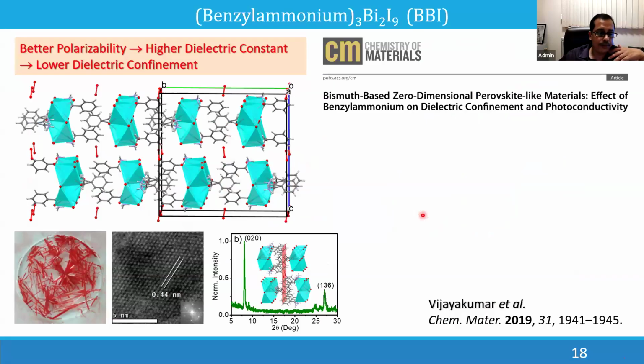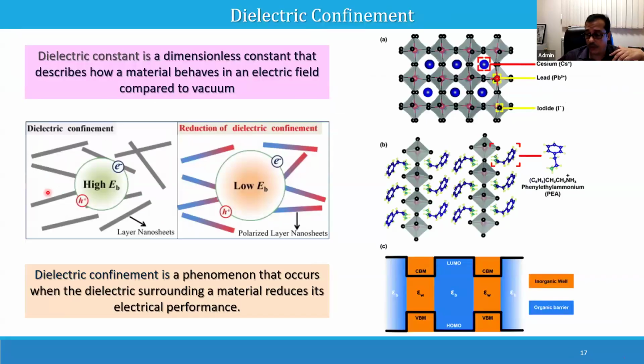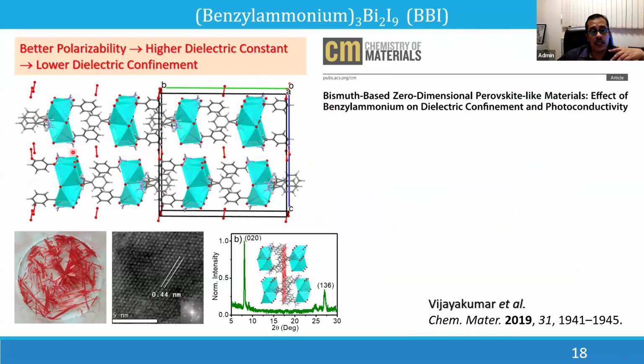What we did is that we incorporated the benzylammonium cation into the perovskite structure. Since it is an organic, aromatic compound, it can have better polarizability. Better polarizability means the charges are there, and those charges actually give a high dielectric constant. That dielectric constant will be very close to the inorganic one, and that will reduce the dielectric confinement. Okay, if the dielectric constants are too different, dielectric confinement is higher. Here we are improving the dielectric constant, and because of that, the dielectric confinement has reduced, and that got reflected